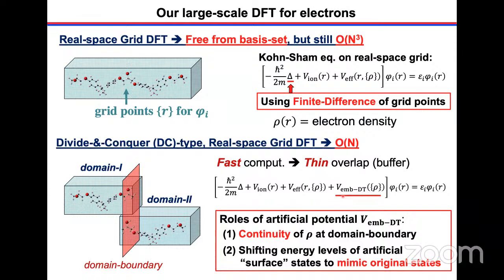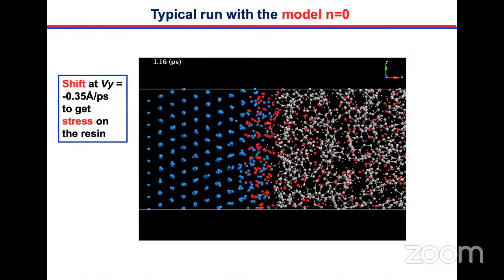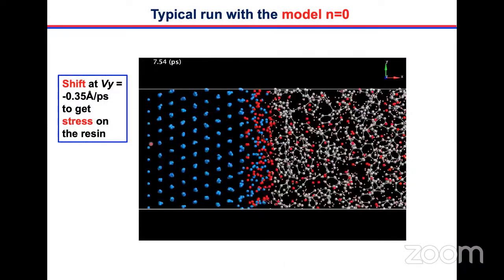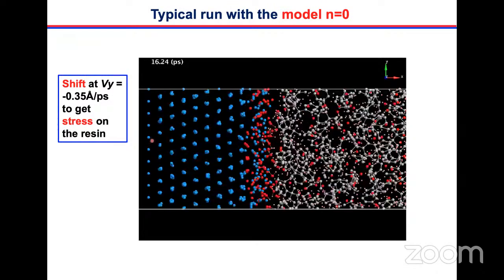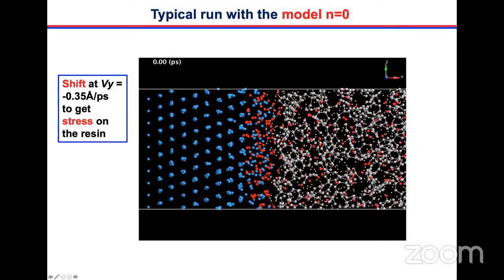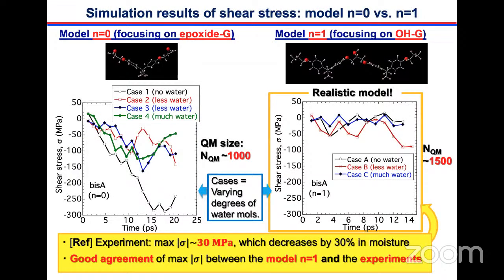This artificial potential has two roles. One role is that it enforces the continuity of the electron density at the domain boundaries. Another role is shifting some artificial levels: because of the abrupt termination of the grid points, artificial surface states emerge, and the energy level is tuned to get the original states. So this is the idea. The left end region of the aluminum is gradually shifted, and then we have some stress field here.